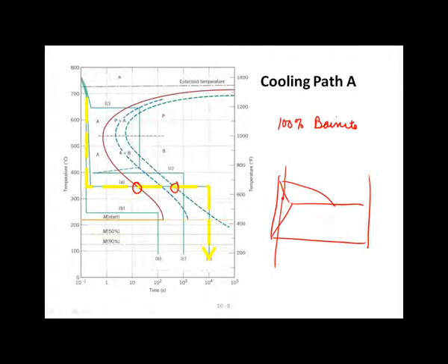I will lock in that alpha phase with a supersaturated concentration of B. So I won't have allowed the transformation of alpha to alpha and beta to happen. You're kind of subverting that natural transformation. And so in that case, there isn't a martensitic transformation. Does that make sense? So sometimes we'll just lock in the microstructure. Sometimes some materials will have this transformation. Otherwise, we're kind of locking that microstructure in. And I'll show you some examples of that as we go through the lecture today, so it'll start to make more sense.